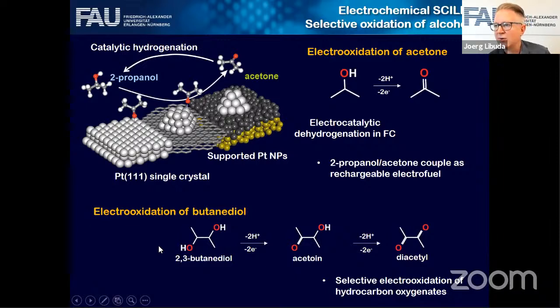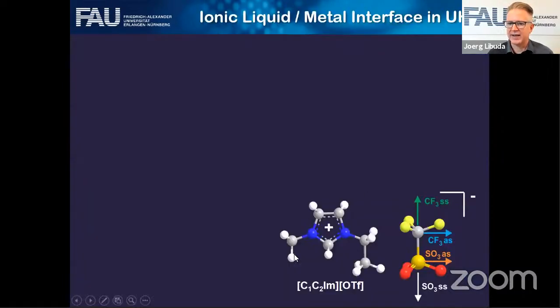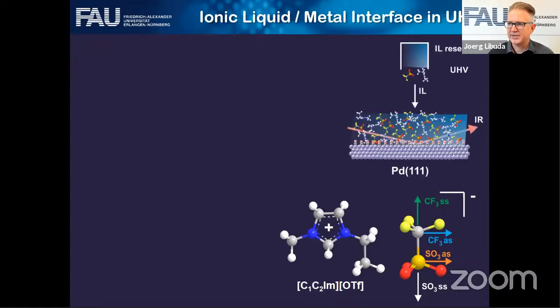But it's also interesting from another point of view. It's the oxidation of 2,3-butanediol. So we have two secondary alcohols that can be oxidized. You make the acetoin first, with one carbonyl group, or the diacetyl with two carbonyl groups. And now the question is, can we control that reaction by an ionic liquid? The ionic liquid that we're using is this one that you see here, the C1C2 imidazolium OTf, a very simple one.